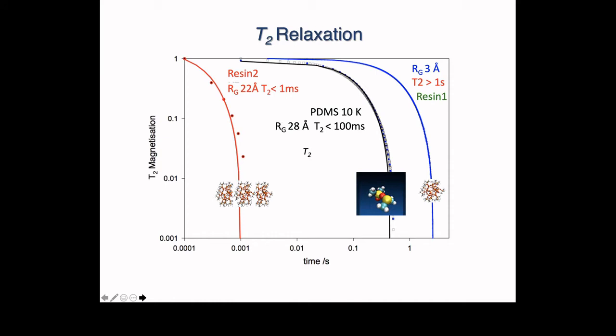And this is just some data that we measured a long time ago from different types of material. So for example, on the left-hand side, we have a resin. This is a polyhedral silica resin, silicon-based resin. It's a solid and it has a very short relaxation time, as you can see by this curve falling very rapidly and coming to zero after a millisecond.